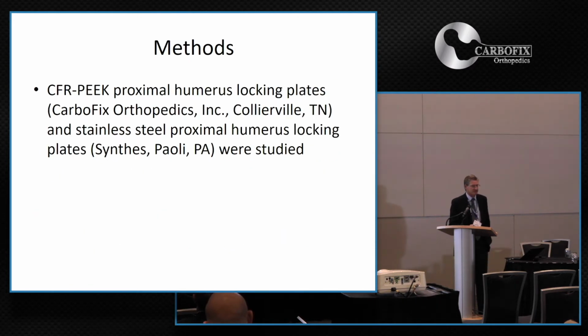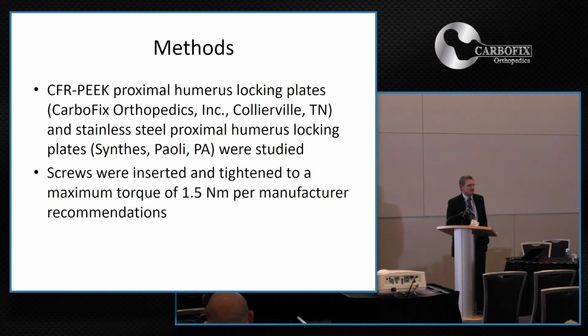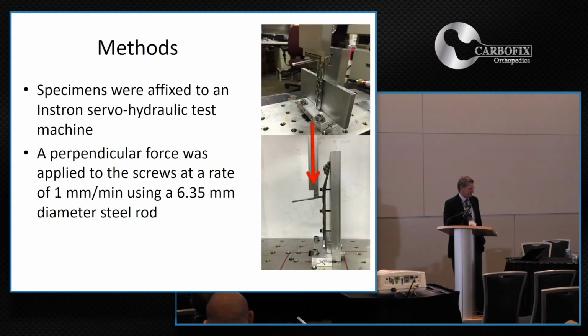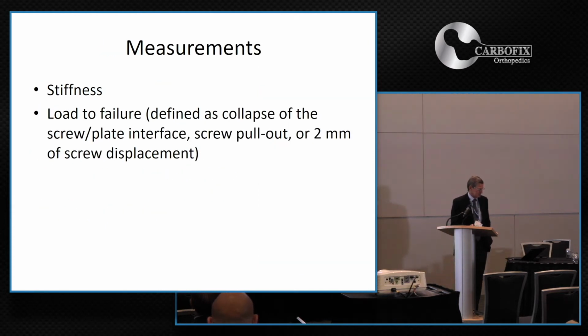We compared Carbofix plates with stainless steel Synthes proximal humerus plates. And all the screws were tightened to the manufacturer's recommendation of 1.5 Newton meters. They were fixed to an Instron servohydraulic test machine, and a perpendicular force was applied to the screw. We measured stiffness and load to failure, which was defined as collapse of the screw plate interface or pull-out or 2 millimeters of screw displacement.